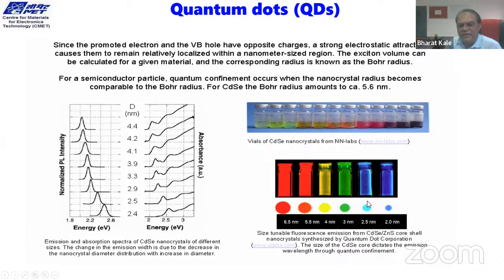This is again something I have taken from the internet. This is cadmium selenide nanoparticles, quantum dots from 2 nanometers to 6.5 nanometers. When we can have the particle size of the material close to the Bohr radius of that material, like cadmium selenide, whose Bohr radius is around 5.6 nanometer, when all the sizes are very close to that Bohr radius,